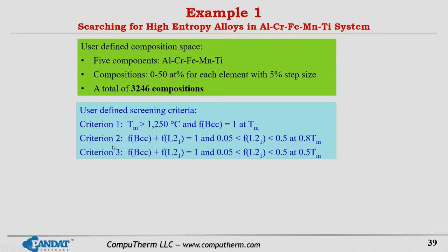The second criterion is that at 0.8 of the melting temperature, we want to have two phases: the matrix phase BCC, plus some precipitate phase, L2_1, and the precipitate phase should be smaller than 50%. The third criterion is that we want to keep this two-phase structure stable until 50% of the melting temperature.